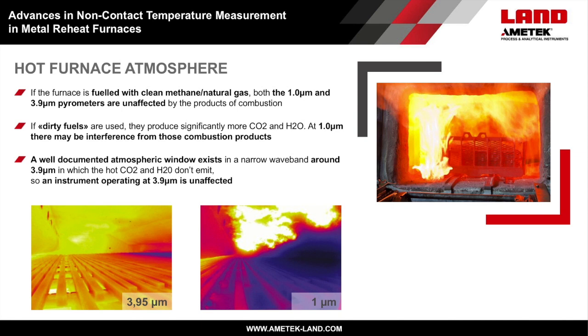See the comparing thermal images at the bottom of the slide, which shows the same scene taken with a 1 micron and taken with a 3.9 micron thermal imaging system. A well-documented atmospheric window exists in a narrow waveband around 3.9 micron, in which the hot CO2 and water don't emit. So an instrument operating at 3.9 micron is unaffected by this atmosphere to provide a clean image and accurate stock temperature readings.